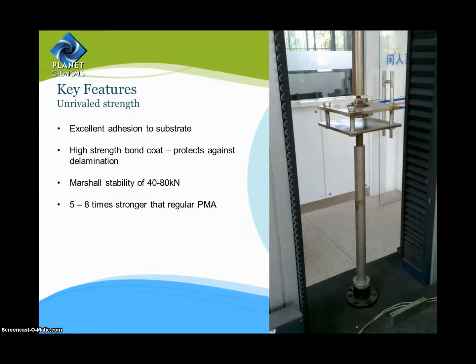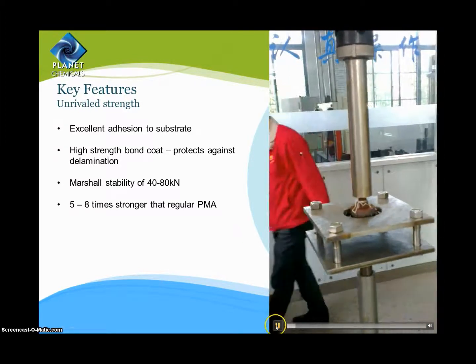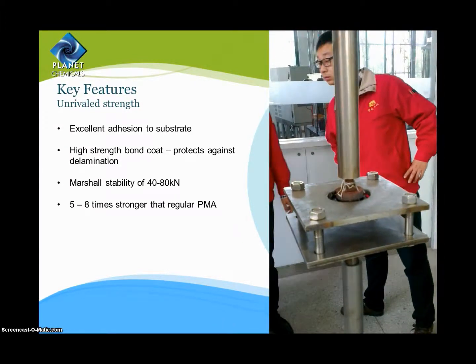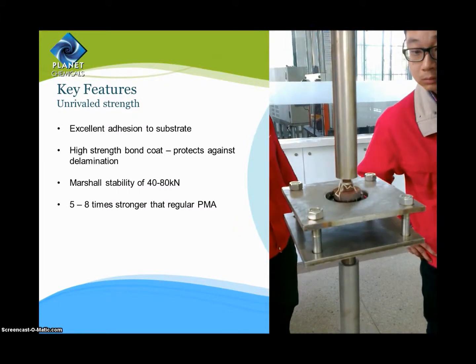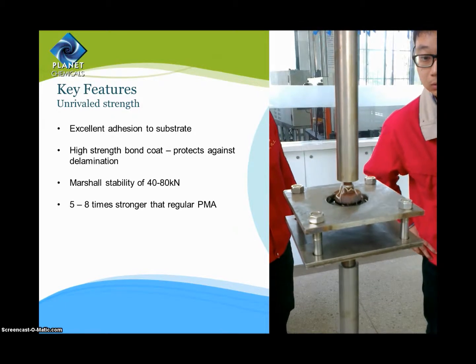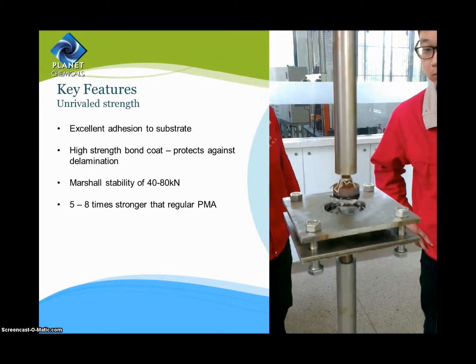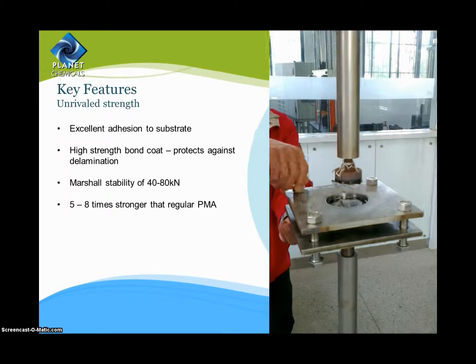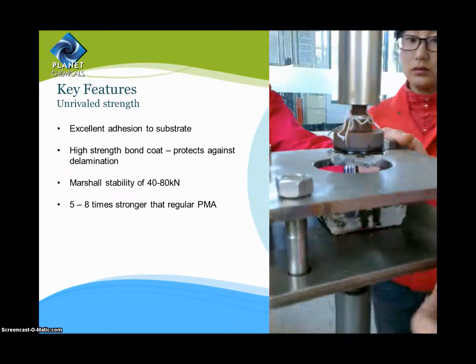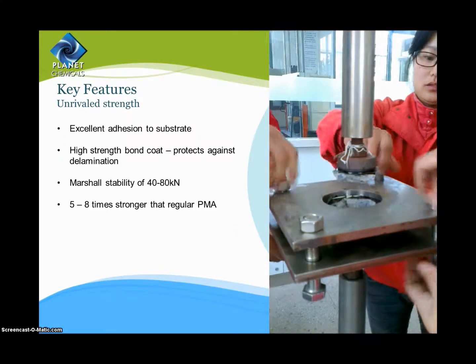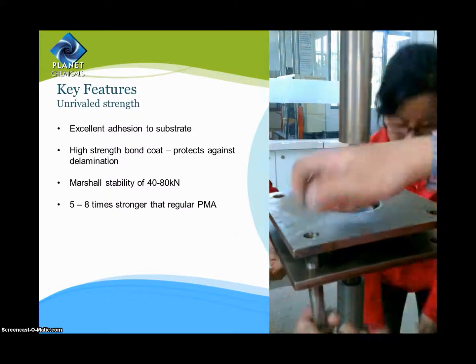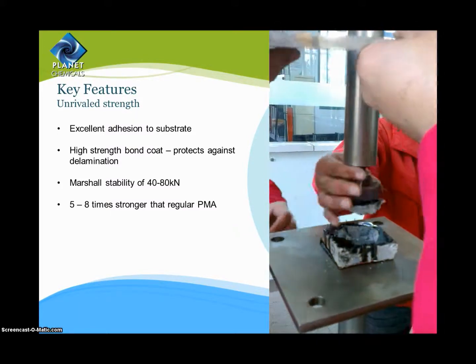The pull-off adhesion test in this video illustrates the adhesion strength of epoxy asphalt. In this test, a circular steel stamp that was glued to a concrete block with a layer of epoxy asphalt bond coat is pulled off to test the adhesion strength of the bond coat. As you can see, the point of separation does not occur along the adhesion surface but on the concrete block. The adhesion of the epoxy asphalt bond coat is strong enough to rip out chunks of concrete before giving way. This further substantiates that epoxy asphalt is resistant to delamination.